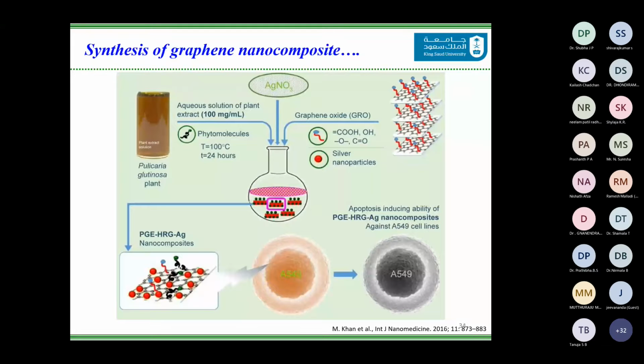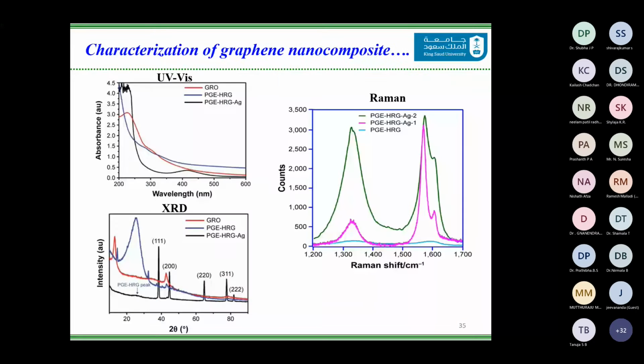As I have shown you earlier also, the UV-vis spectra reveal that the plant extract is reducing the graphene oxide, which appears at around 240 nanometers, as well as there is an emergence of a peak between 380 and 420, which is indicative of the reduction of silver nanoparticles. So here we were successfully able to reduce the graphene oxide using the plant extract, as well as deposit silver nanoparticles on the surface of the graphene.